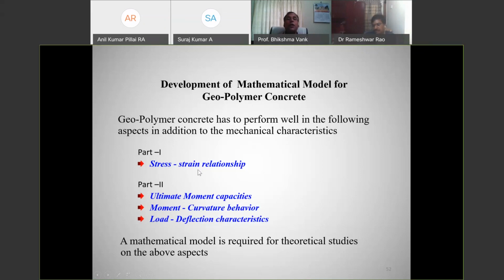And we have casted the cylinders for the target strength mix proportions which we obtained, and for those target strength values, we have casted the cylinders, then tested them and developed the stress strain curves. These stress strain curve values are superimposed onto the RC members, and theoretical values have been obtained. And experimentally, again, we have done the beams and then compared the experimental and theoretical values. So this is how the investigation has been done.